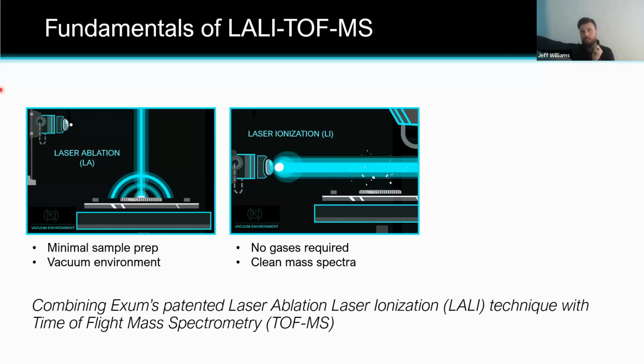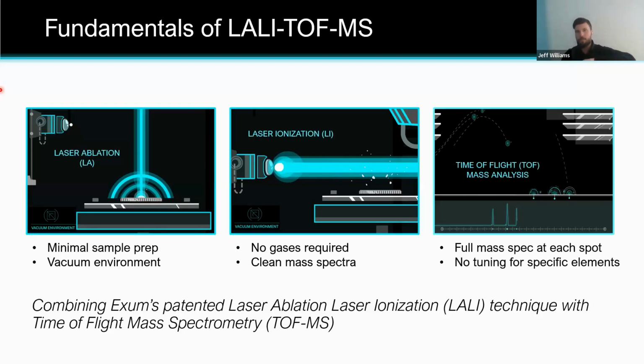And then we can push those ions into a time-of-flight mass spectrometer. So we can ionize basically every element on the periodic table. And then every laser shot, we kick it into what's called a time-of-flight mass spectrometer. So time-of-flight mass specs basically work like kicking a soccer ball or kicking a bowling ball with the same energy. The soccer ball is going to go a lot faster, right? And so that's what happens with lithium versus uranium. Lithium's going to fly very fast down our tube, and uranium's going to fly very slow.